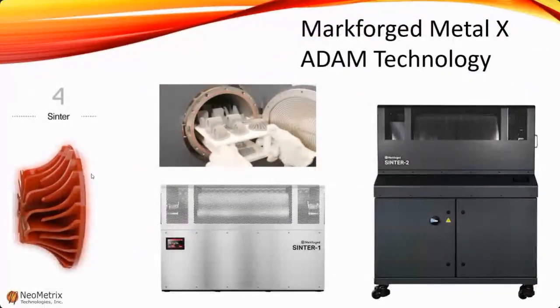Sintering transforms a brown part into a fully metal part. To do this, the temperature is ramped up slowly to burn away the trace amounts of remaining binder material. As the temperature ramps up closer to the melting point of the material, the metal particles fuse together to create a strong metal part. The part is heated from room temperature to about 85% of the metal's melting point, and then it slowly cools down.